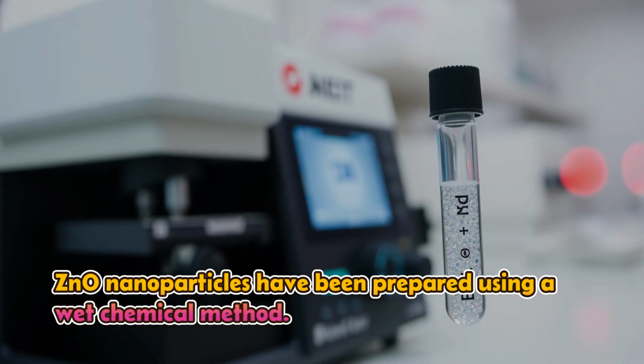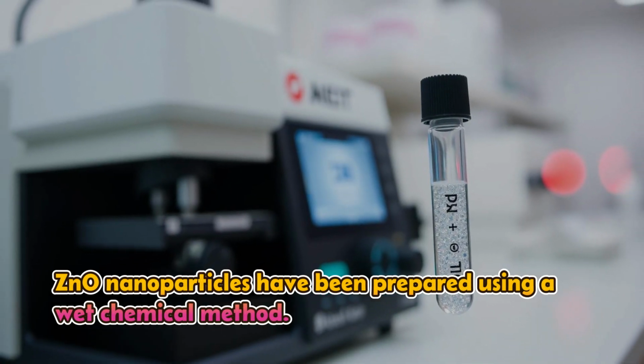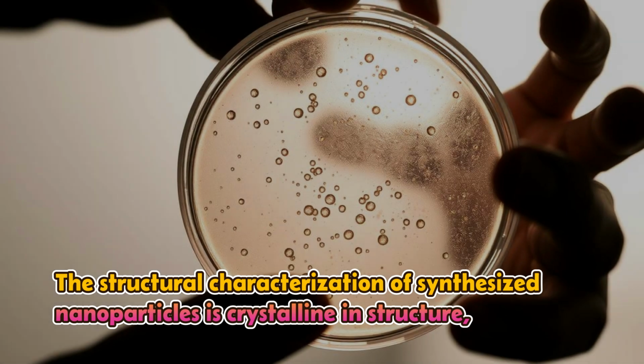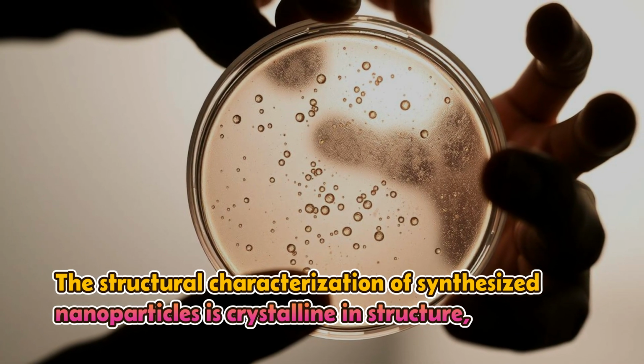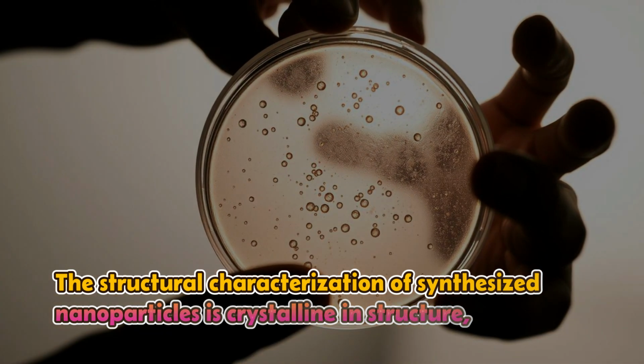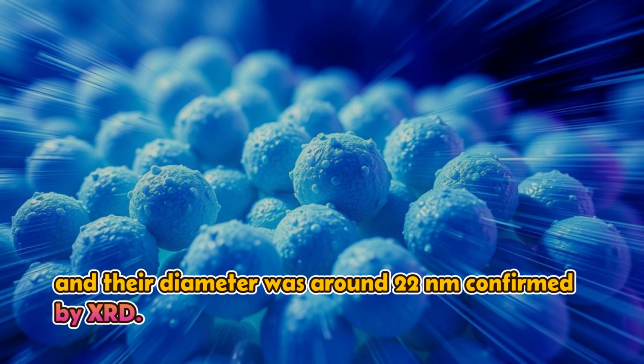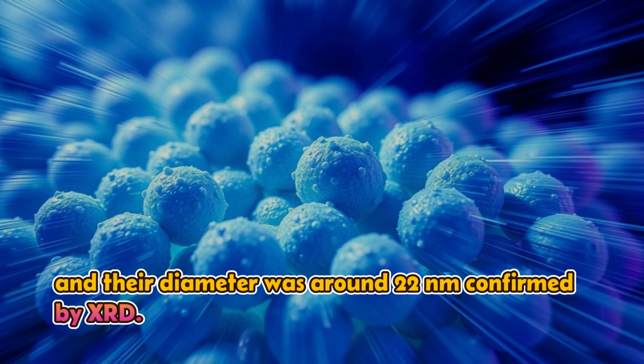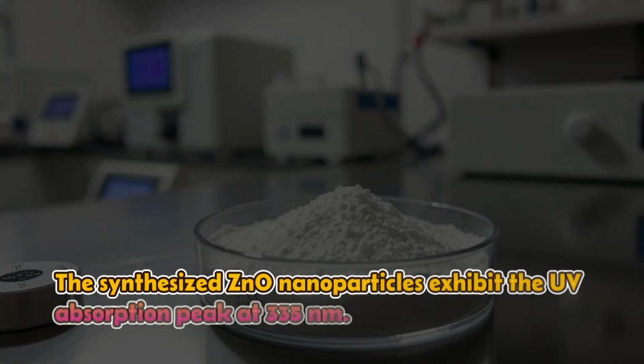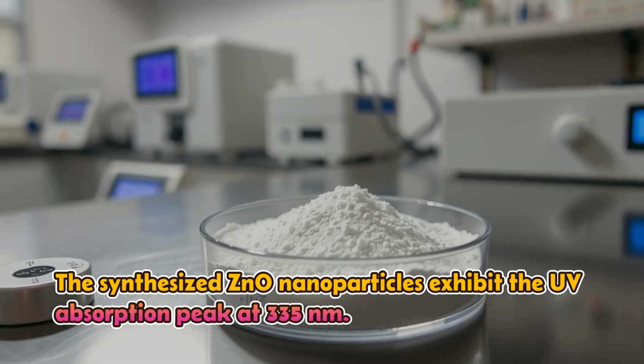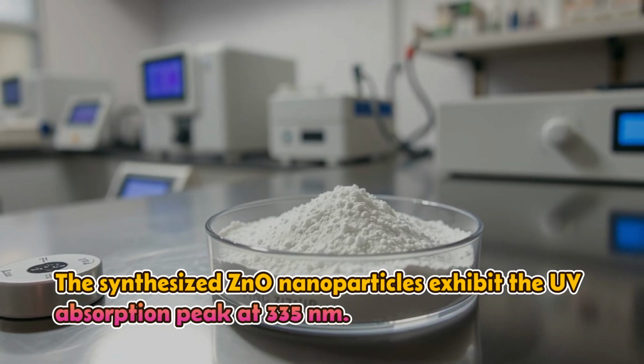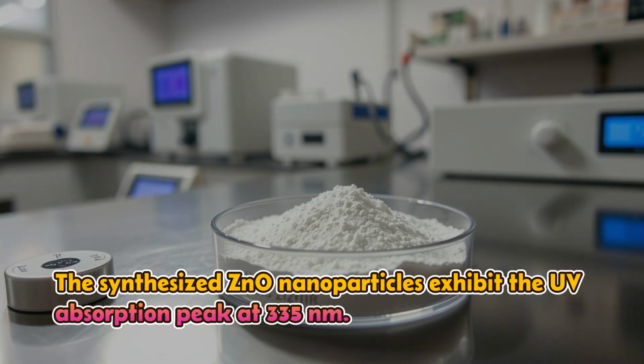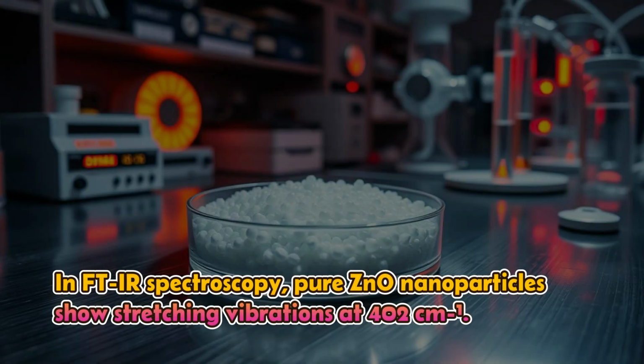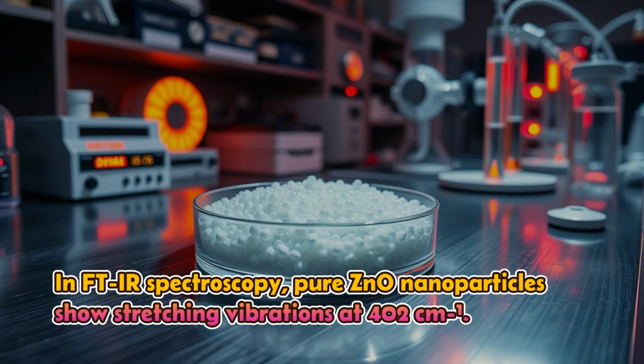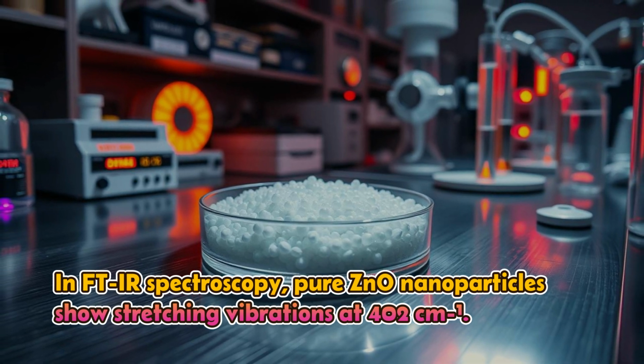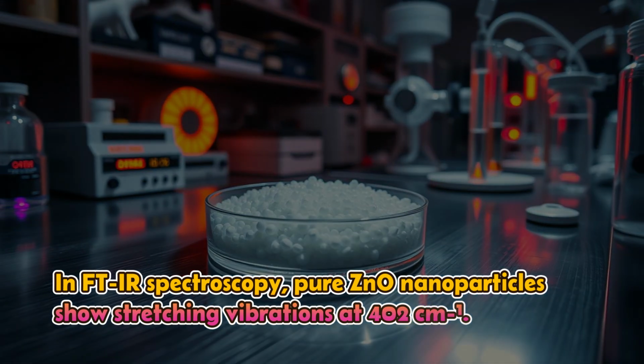ZnO nanoparticles have been prepared using a wet chemical method. The synthesized nanoparticles are crystalline in structure, and their diameter was around 22 nanometers, confirmed by XRD. The synthesized ZnO nanoparticles exhibit a UV absorption peak at 335 nanometers. In FTIR spectroscopy, pure ZnO nanoparticles show stretching vibrations at 402 cm⁻¹.